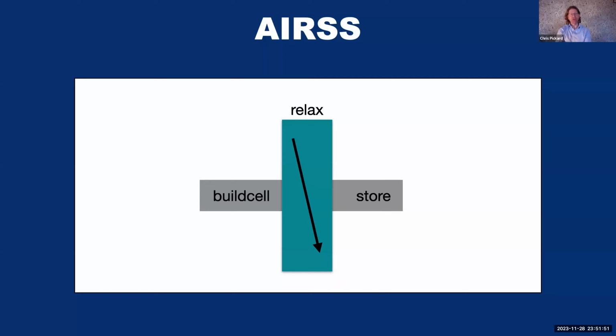And I'm going to give an example of this here by reflecting back on effectively what is an AIRSS, an ab initio random structure search. In an ab initio random structure search, we build a unit cell, we feed it into a code like CASTEP, and we relax the structures to the nearest lowest energy, and then we store the result. And this is the optimization that we do.